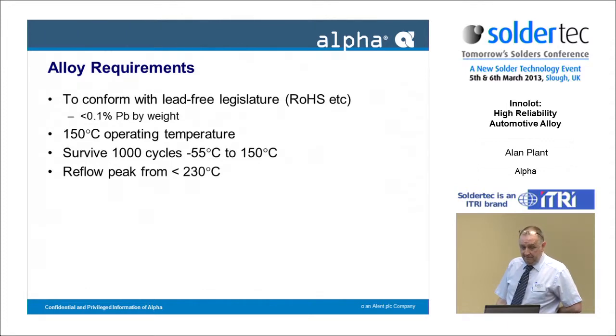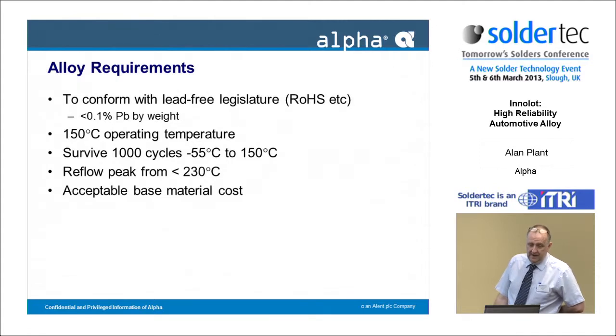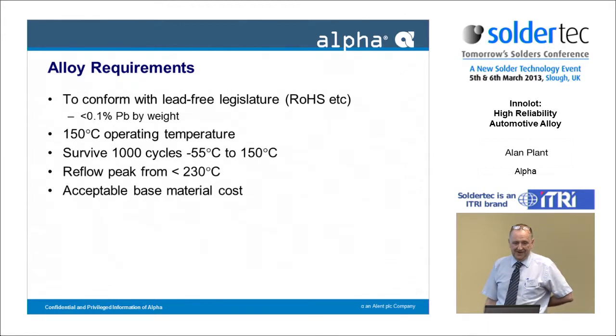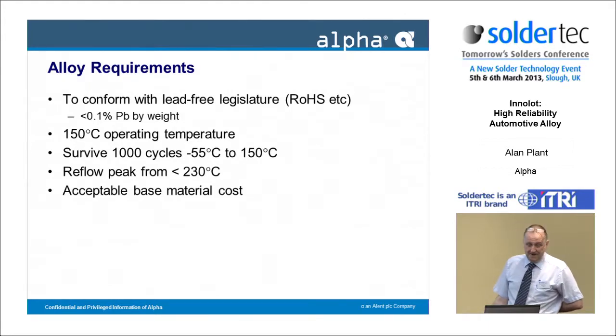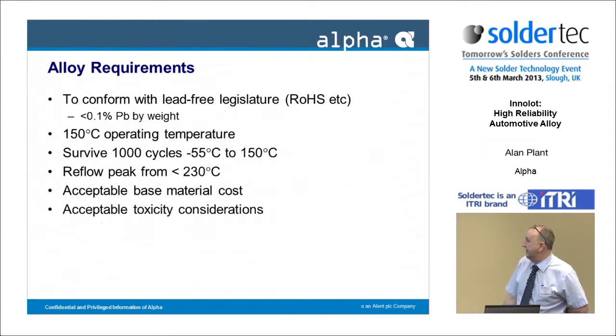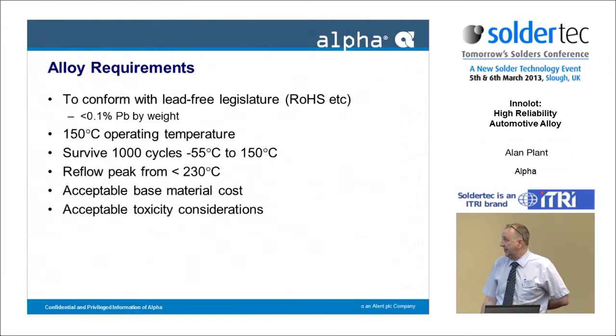Try and get a reflow temperature, ideally less than 230. Acceptable base material costs. There's no use producing an alloy and then using those wonderful alloying elements, costalotium or unobtainium, which do tend to occur. It's great, but people have to use these in volume, and therefore it's got to be cost effective. And acceptable toxicity considerations.